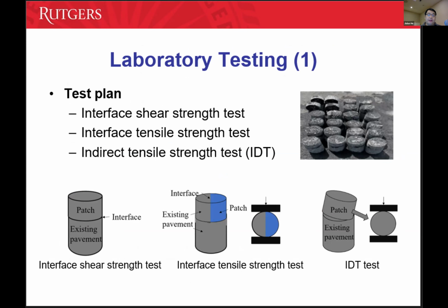Ideally, we want the shear bonding at the edge, but because the geometry is very difficult, we use the bottom surface as the interface shear testing. And we use the edge surface for interface tensile. So it's still interface bonding, but it's in the tension mode. And then we also use the patch material itself for the IDT, indirect tensile strength.